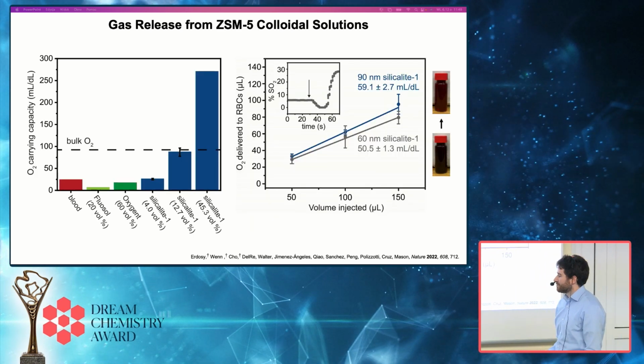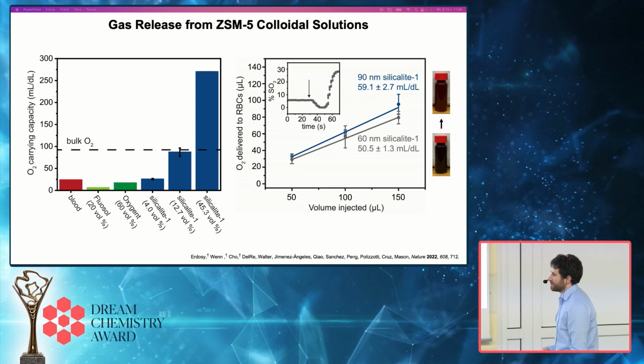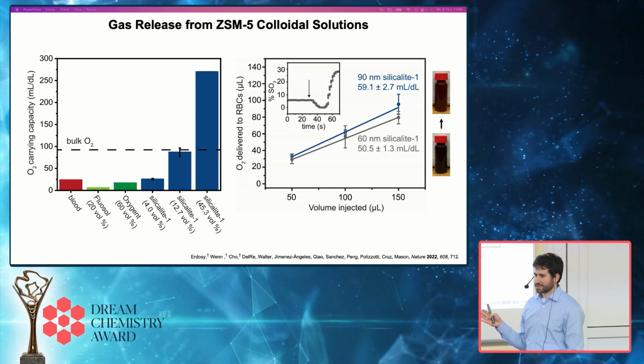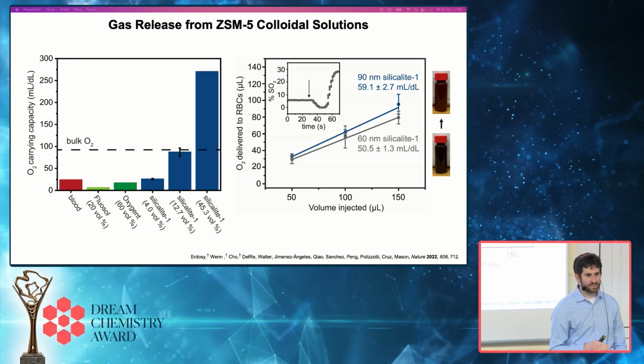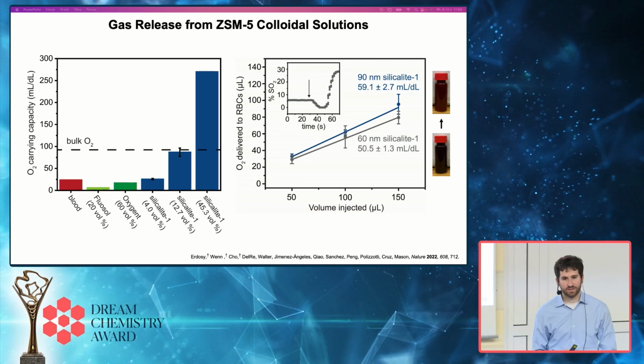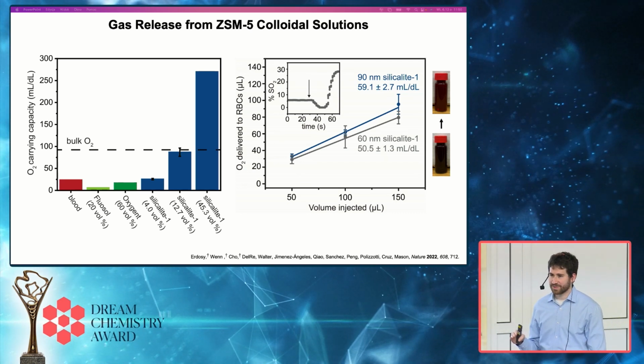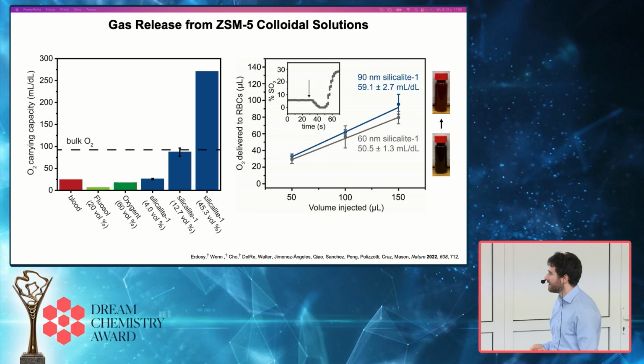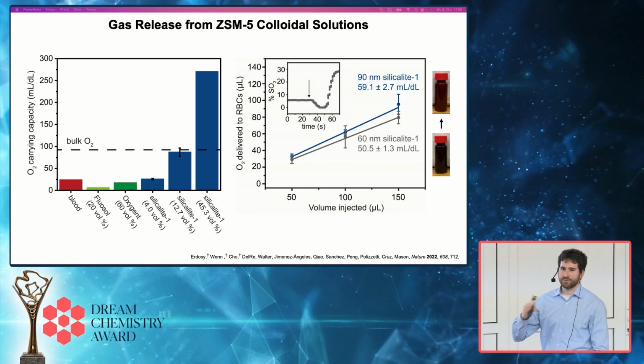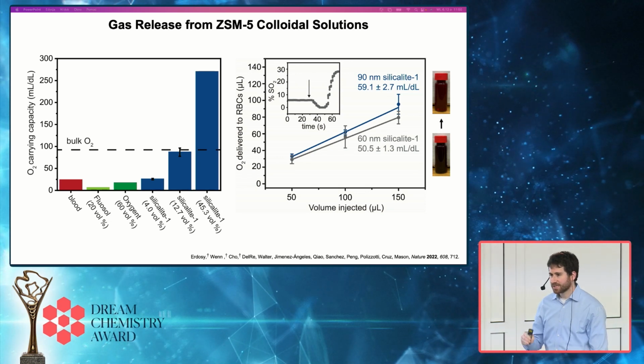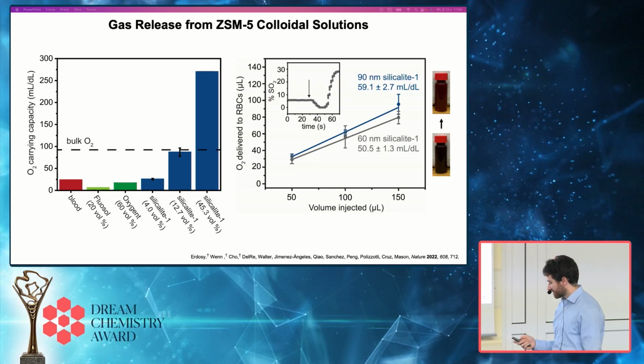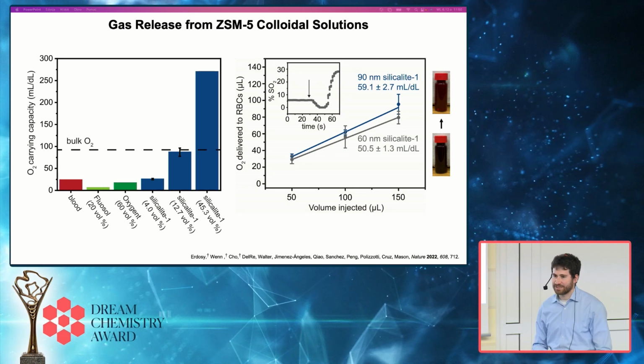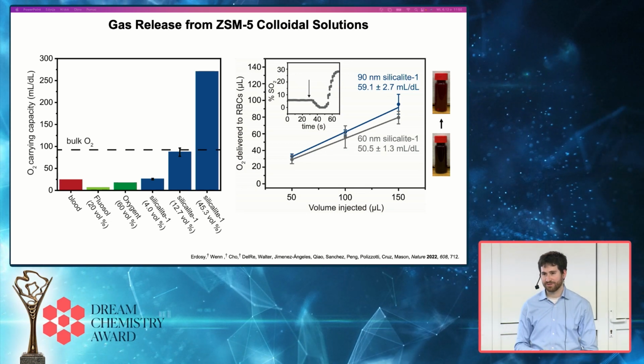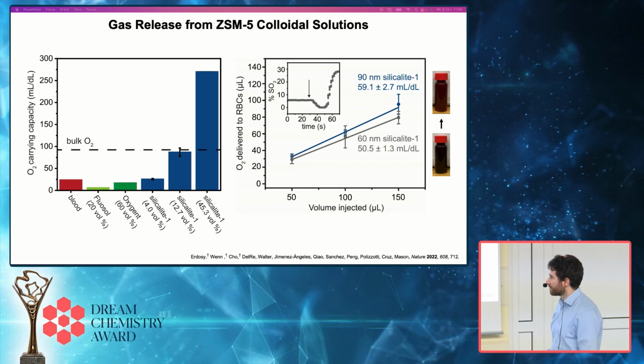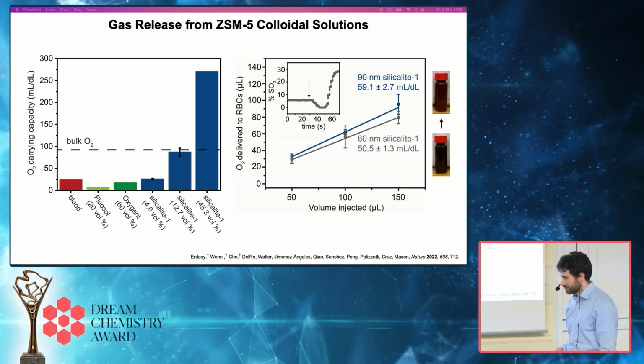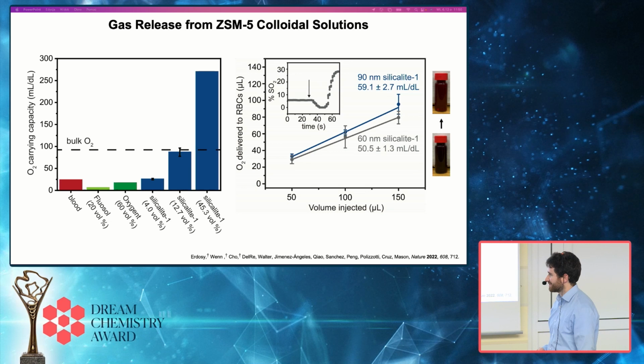So we did one proof of principle experiment initially where we showed that we could take these oxygenated silicalite-1 solutions and inject them into deoxygenated donated human blood and do normal blood gas analysis measurements, just like you would get if you see a doctor, to quantify change in oxygenated hemoglobin and measure how much oxygen is released. We found that the oxygen carrying capacities that we measured are again in line with what we measured using these other techniques in pure water. And so this got us excited about exploring biomedical applications with these solutions.